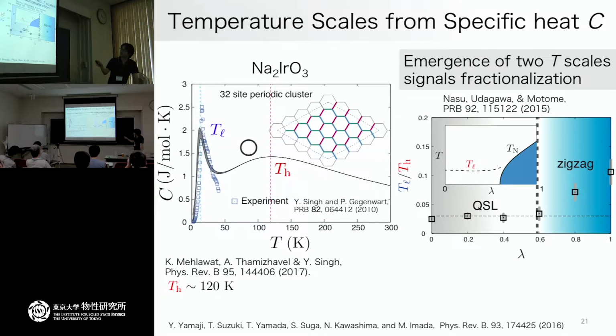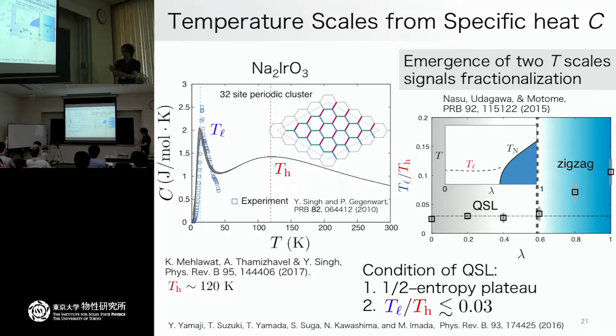And by using these two peak temperature scales, and taking a ratio of these two temperature scales and plotting it as a function of lambda, we found another interesting physics in this system. Inside the quantum spin liquid phase, this ratio remains constant around 0.03. But in the magnetically ordered phase, it rapidly rises. So in this system, if you measure the heat capacity and take a ratio of the two temperature peaks, you may find a quantitative condition to obtain the quantum spin liquid phase.